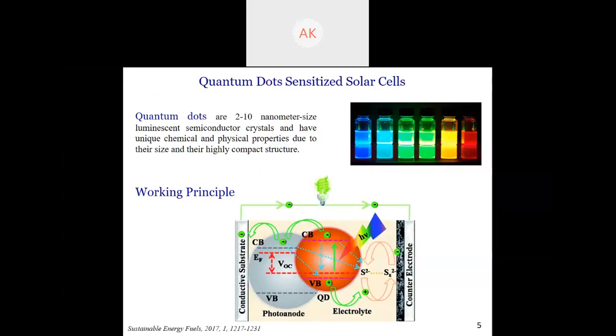The hole remains in the valence band while the electron gets transferred to the conduction band of the large bandgap semiconductor, TiO2 or ZnO, whatever the case may be, in the photoanode. This causes charge separation. Now, this ultra-fast charge injection from the conduction band of the quantum dot to the conduction band of TiO2 or any other large bandgap semiconductor is followed by quick scavenging of the hole that is left behind in the valence band of the quantum dot by the reduced species of the redox couple, that is polysulfide, and then the electron that is there.